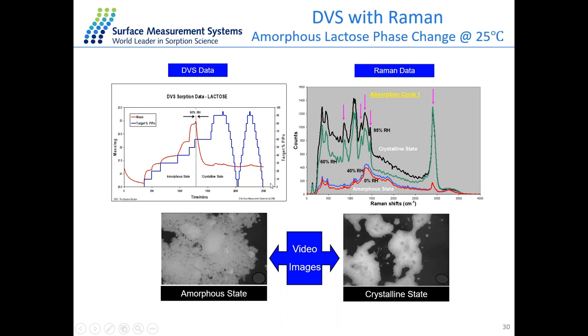Looking at the second cycle is useful, because what we can see is that this phase change is irreversible and very different from what we obtained from the first cycle. We can see that this change is a permanent change from an amorphous to a crystalline state.